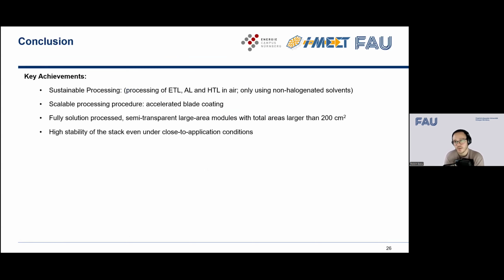So the key achievements of what I was talking about: we achieved sustainable processing because everything was done in ambient conditions with non-halogenated solvents. We have a scalable processing procedure with accelerated blade coating. And it's a fully solution processed stack that is semi-transparent, and we can show that we can also do it on quite large areas with a comparably simple setup. And the stack also shows a high stability under close to application conditions.